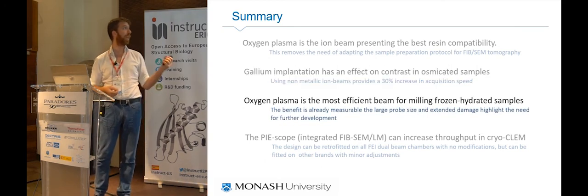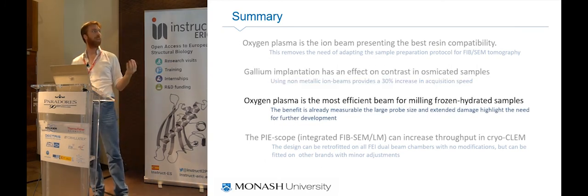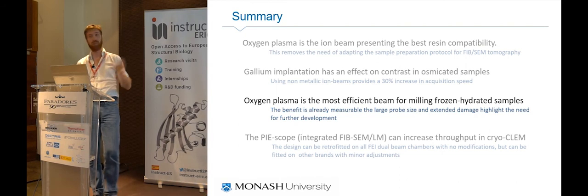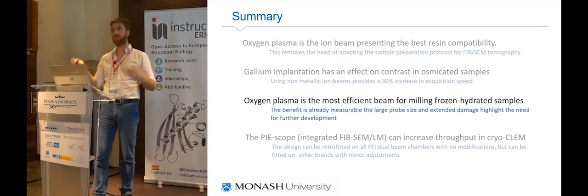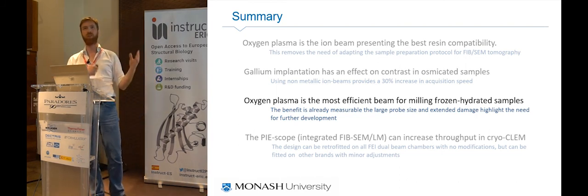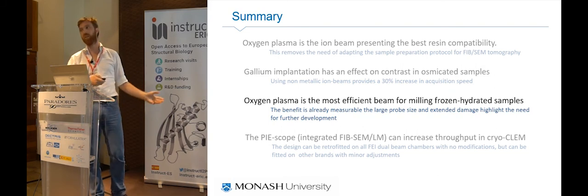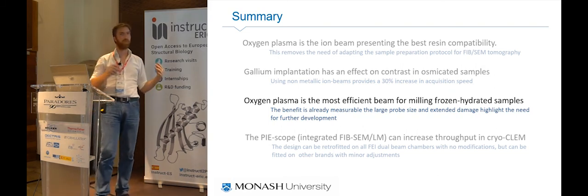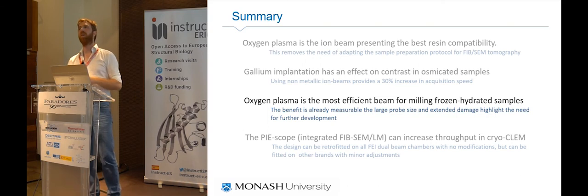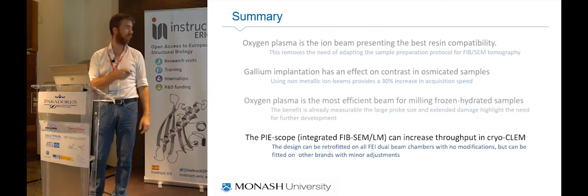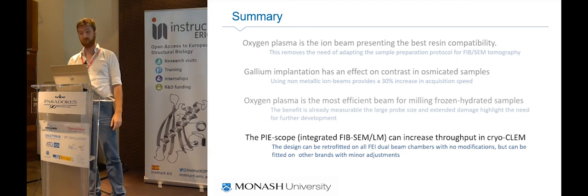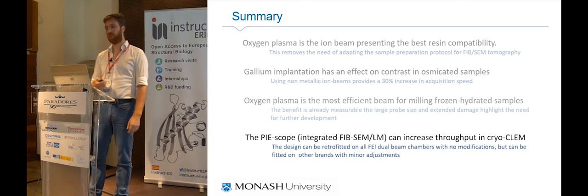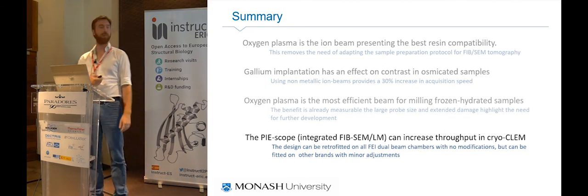The oxygen plasma is the most efficient beam also when it comes to milling frozen hydrated samples, but it is problematic because it does damage a lot. So it only works for thick lamellas as of today. So it's probably something that will be very valuable for lift outs. And then the integrated light microscope is just working. So if you need one, just let me know. It can fit on pretty much any dual beam.